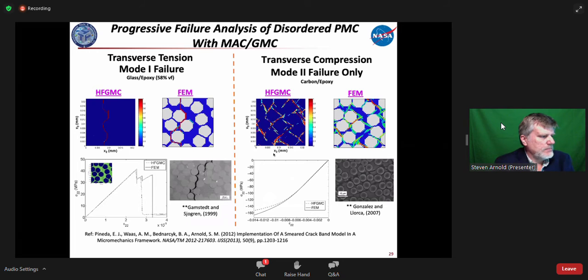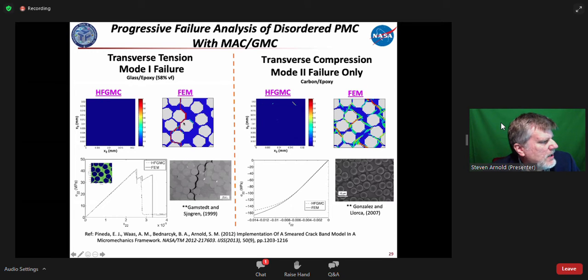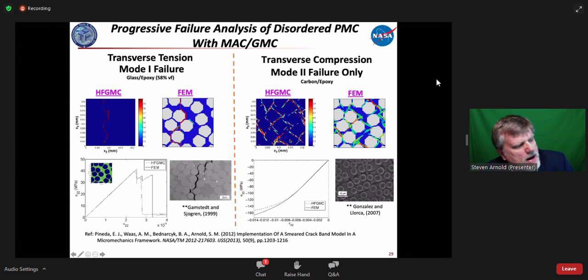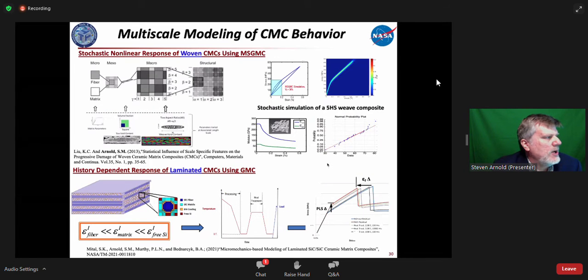Here's just an example again of a progressive failure analysis of a disordered PMC with MAC/GMC, where on the left here we're showing the transverse tension of a glass epoxy system, or the mode 1 failure, and you can see the singular crack is able to be predicted. Here's a finite element, and the agreement's reasonably well between the two. And then on the right hand side is a transverse compression case, which is a mode 2 failure, and we're able to pick up the diverse cracking that takes place under that, and obviously depending upon the disorder of the microstructure, the values change.